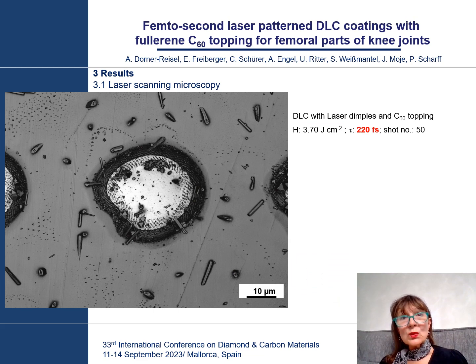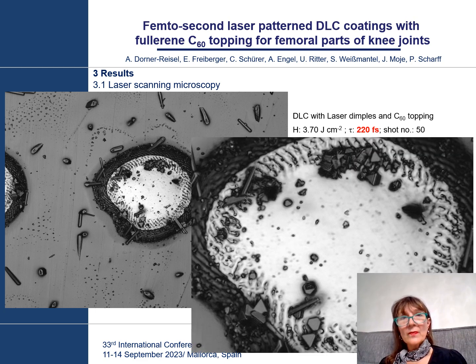Laser scanning microscopy enables us to dive deep inside one single dimple. We can recognize the exposed cobalt, chromium, molybdenum substrate very well. And we see that there is an additional micropattern, so-called LIPSS pattern, at the bottom of the dimple in the cobalt, chromium, molybdenum substrate. The C60 needles seem to adhere especially well at that pattern. In addition, we have also polyhedral crystals of C60.